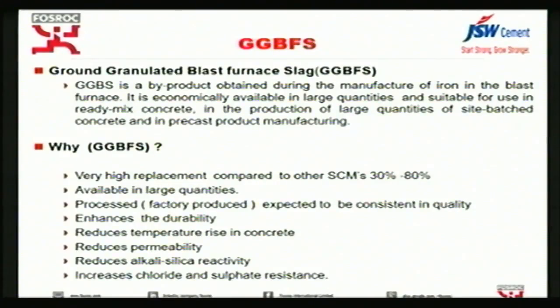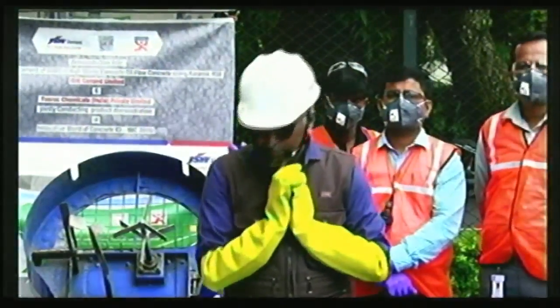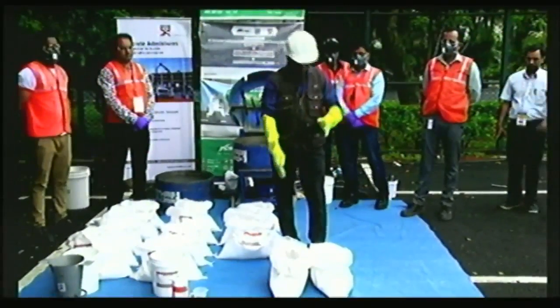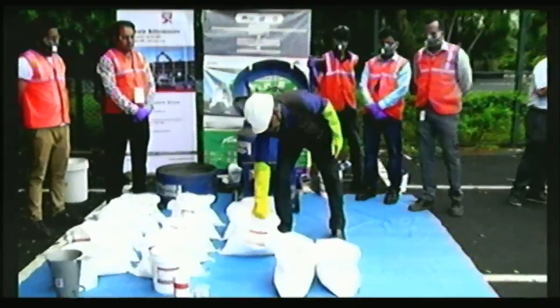This is the second seminar on replacement of cement by ground granulated blast furnace slag. Apart from that, we would like to emphasize the point that if there are some variations at site, with the same mix design and the same kind of chemicals, even with variations in aggregates, the mix will still be the same. That's something we always have as a problem at site. The fine aggregates get into the trouble of not getting things right. Right now you can see here, this is a high volume of GGBS and very little amount of cement. So you are going to have only 30% pure cement and the balance is GGBS. And what we have here is typically zone 2 sand and zone 1 sand. You can see that coarse materials are there.